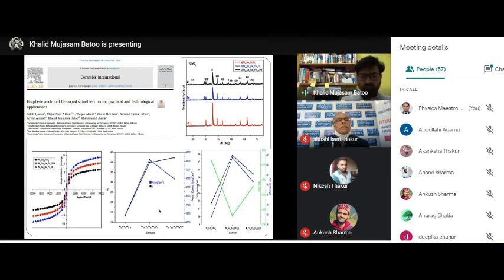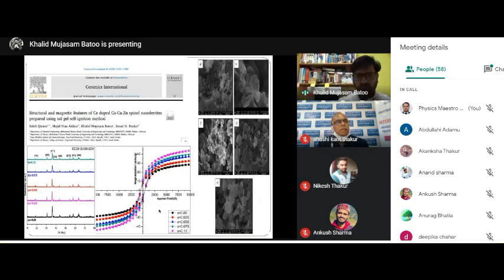We saw the MH loop, MH showing up to 20 EMU per gram. However, when we tried the same material without the graphene, we saw that the magnetic properties were better. So this was not helping us the way we thought graphene could be used, which is one of the revolutionary materials nowadays.